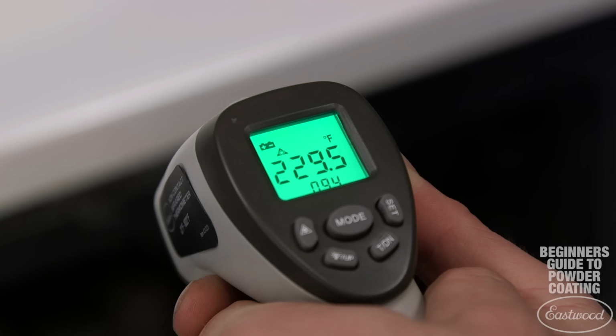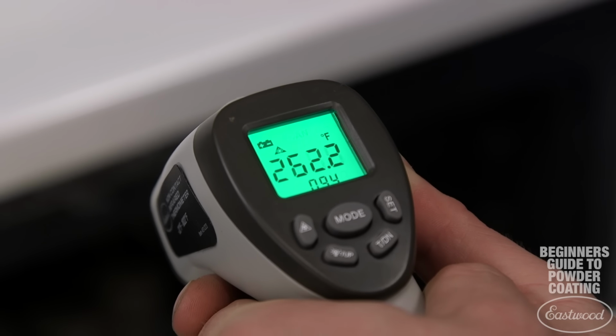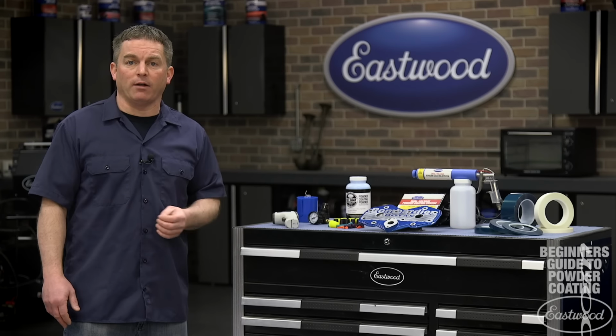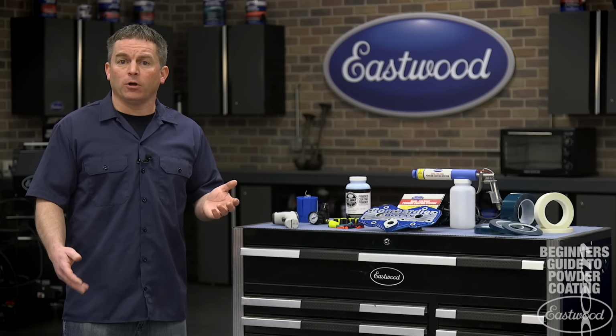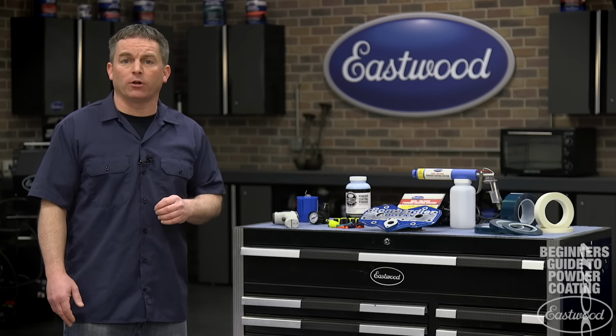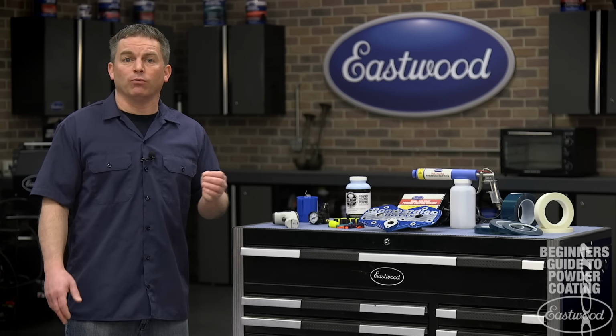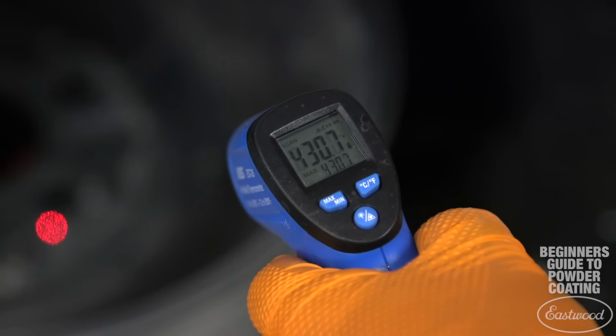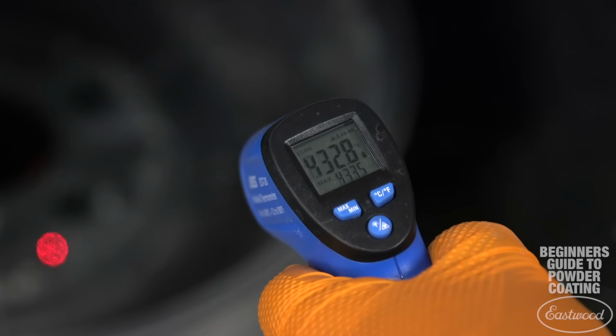An IR thermometer is helpful for determining the temperature of the part if it's preheated or being hot flocked. An IR thermometer will tell you the exact temperature of the part you're coating, while the oven thermometer will read the air temperature, and there could be a difference between the two, especially if it's a thick cast part.